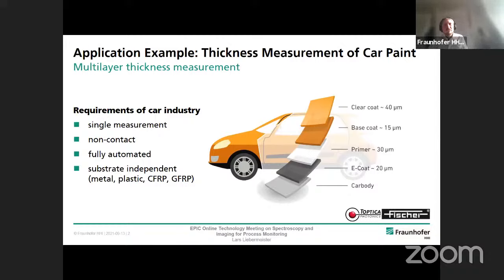So if you look at this car paint, it's a structure of multiple layers in the tens of micron range. And the task you actually get there is to measure the thickness of all the individual layers with a single measurement. Of course, this measurement has to be non-destructive, but also non-contact, since the paint is fresh and has to stay shiny and so on. Also, of course, the process has to possibly be fully automated.